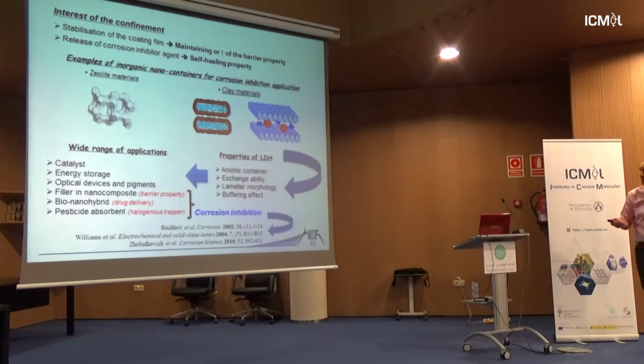Because of course, when you are using some organic active species, they are very active, but not in a good way. They can be active against the polymer chain. They can migrate out of the polymer coating because they are of small molecular weight, so they can diffuse. By diffusing, of course, they can break down the integrity of the polymer coating. So when you have moisture, you will have a path of diffusion for water. So the good thing is to trap the active corrosion inhibition species. And to do so, you may use zeolite, that's been done, halloysite, and of course LDH, because of, as I mentioned previously, the good thing about all the chemistry involved in LDH and the tunability that you have for this type of materials.